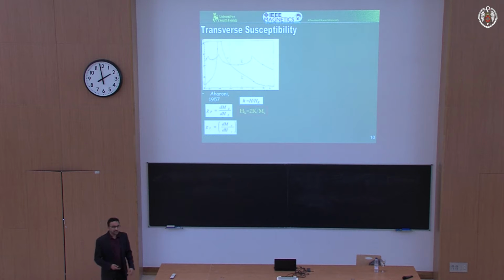We were motivated by a very old paper by a theorist, Aharoni, from Israel. He published this in 1957. It's an analytical calculation of both components of the susceptibility, the parallel longitudinal component and the transverse component. This was in the Bulletin of the Israeli Physical Society. It was hard to get, but here it is. This is the original scan of the graph. So what he did was he took a single domain particle, a Stoner-Wohlfarth, T equal to 0 calculation, and he plotted the conventional susceptibility, which is nothing but the derivative of your magnetization curve, and the transverse susceptibility, which is a tensor. It is the projection of the magnetization in the perpendicular direction.